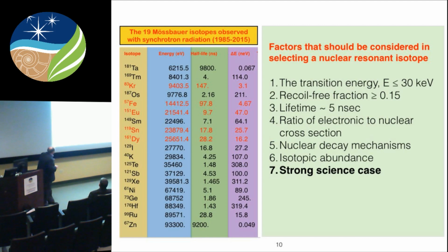To get the Mössbauer signal. When we measure the inelastic spectrum, we go away from the resonance energy to compensate for this. But if this recoil-free fraction drops below 15%, the harmonic approximation collapses, and the data becomes difficult to evaluate. When you go to the 60-70 keV range, this number becomes a few percent, and that's why we don't use it.